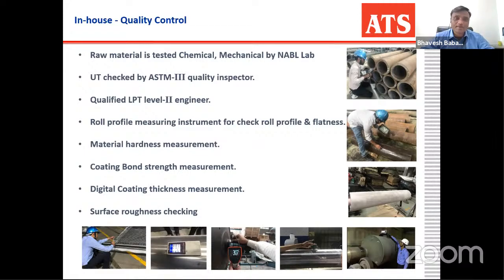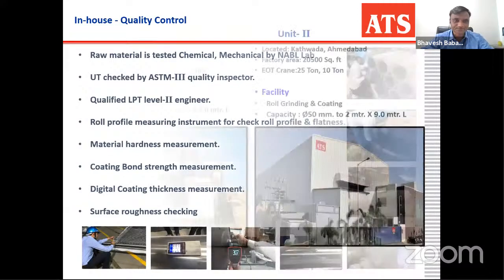We also use a roll profile measuring instrument for checking the roll profile and flatness, because each and every roll has flatness. The profile is very important because the profile gives the good shape and good quality of the sheet. We also check the material hardness, coating bond strength, digital coating thickness, as well as surface roughness. These are all the parameters we maintain during our coating and manufacturing stage.